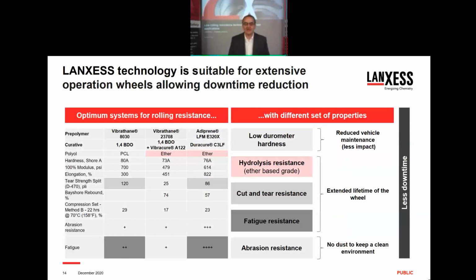And it would depend on application. So for instance, a wheel that's a torque wheel, a drive wheel, or a brake wheel generally will be more driven in terms of lifetime by fatigue. If it's an idler wheel, or a drive wheel that's going over lots of debris, contamination, dock plates, if it's run outside, a lot of times it's that cut and tear. So on a dirty floor or with a lot of debris, the cut and tear usually is the main culprit for failure. And then if it's more of a drive or a torque wheel, we look at fatigue there.